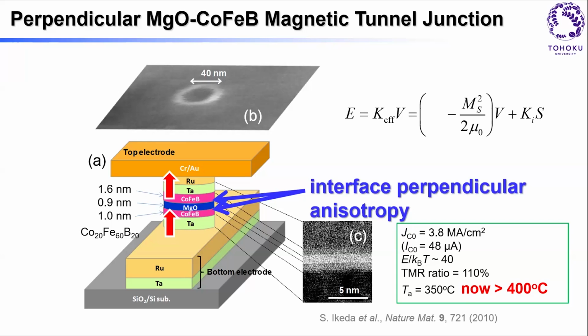People never thought about it, but we did some systematic investigation to see how things change by thinning cobalt iron boron. And just by thinning cobalt iron boron, you get a perpendicular easy axis. That's because here's a shape anisotropy, this classical anisotropy that brings your magnetization in plane. But here's another anisotropy at the interface that tries to bring magnetization perpendicular to the plane.